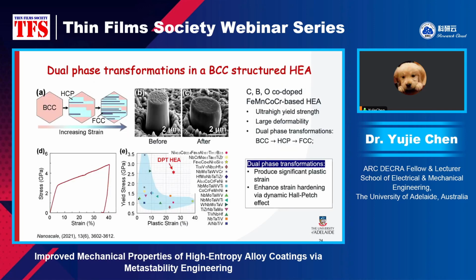And in a following study, we introduced the dual phase transformation to a BCC structure high-entropy alloy through interstitial co-doping. But this time the interstitial element content is very low. Our BCC structure high-entropy alloy shows an excellent combination of strength and ductility. We can see from the barrel shape of the compressed micropillar. And where does this ductility come from? It's from this two-step phase transformation from BCC to HCP to FCC. So the mechanical property, from this Ashby plot, we can see surpasses many other high-entropy alloys in the literature.